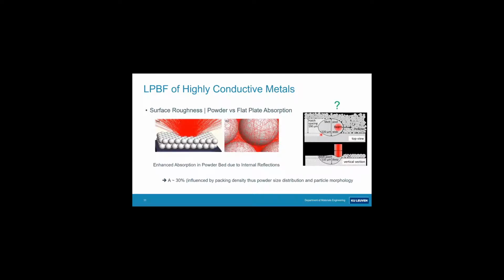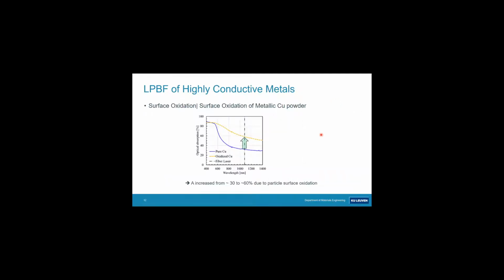But if I remember well, Professor Logé yesterday also talked about absorption phenomena, and he also pinpointed the fact that your laser beam is actually, for the majority of the beam, shining on a liquid melt and not as such on a powder. And so the advantage of a powder bed is then completely annihilated, and we should try to improve, especially the absorption behavior of the melt pool.